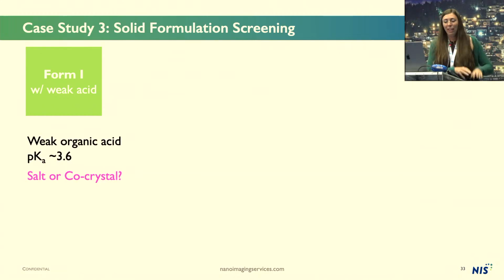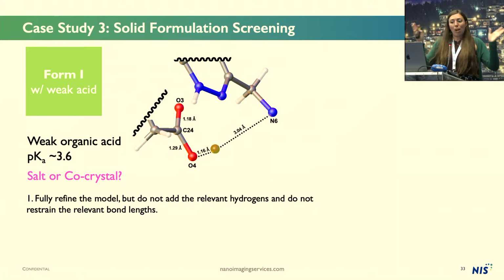All right, so in looking at this structure, one of the big questions we had, and one question that you always have in pharma, is: is this a salt crystal or a co-crystal? Has proton transfer occurred between this weak organic acid that they were using and their active pharmaceutical ingredient, their API? And thankfully, micro-ED is very well suited to address this problem. So typically, when approaching a problem like this, we will do a pretty conservative refinement of their structure. So we'll model the whole rest of the molecule, but we'll leave the proton in question alone and not model it until the very, very end.